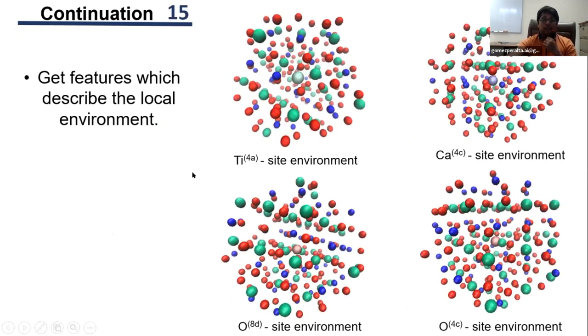Now, the features describing the chemical environment refer to the neighborhood within a certain cutoff radius, depending on the crystallographic sites occupied by the atoms. In the slide, I show you the 4 neighborhoods around the 4 crystallographic sites in the calcium titanium oxide with the orthorhombic symmetry. The titanium atom locates in sites with the 4a Wyckoff site. Similarly, calcium locates in sites with 4c Wyckoff site. And in calcium titanium oxide with the orthorhombic symmetry, there are 2 types of oxygen, since the oxygen occupy 2 kinds of crystallographic sites, one labeled as 8d and another one labeled as 4c.